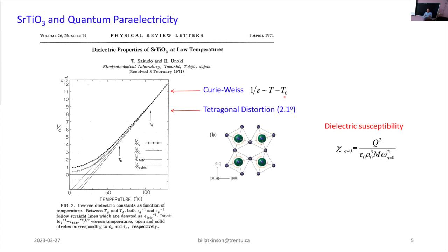There is a small crystal structural transition that happens at 105 Kelvin. You get tilting of the oxygen octahedra. This is very common in perovskites. In strontium titanate, it's not a big enough thing that we usually worry about it. It's quite a small distortion, but it's there. It splits the dielectric constant into A and C components.